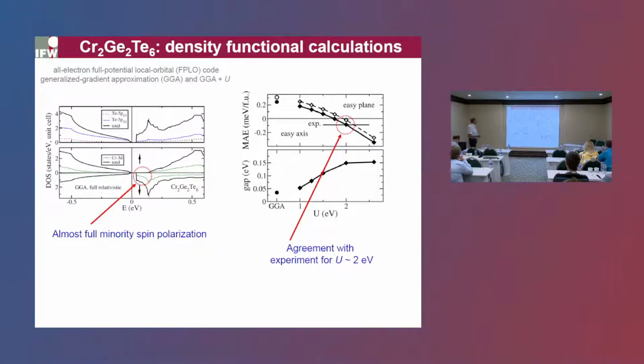Our theory collaborators performed density functional calculations using the all-electron full potential local orbital code, the generalized gradient approximation, and also, what was important, adding the correlation energy U. One important finding in this computational study was the band structure. It turns out that the conduction band is gapped, because it's a semiconductor, but it is fully polarized at low energies. One has here almost full minority spin polarization. It suggests that if, for instance, a single layer could be gated and doped by electrons, this will generate a fully polarized electron gas, which is very useful for potential functionality of this material.